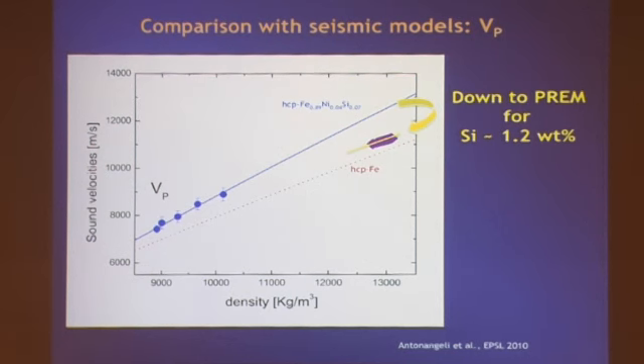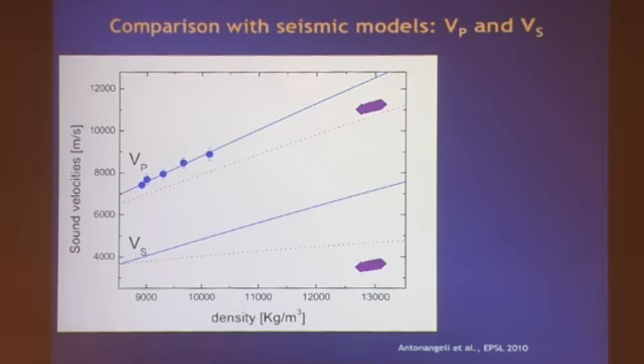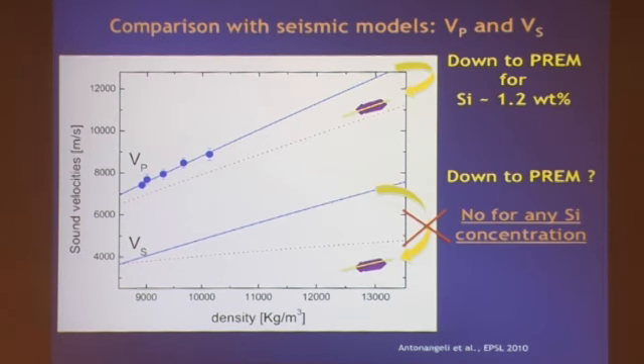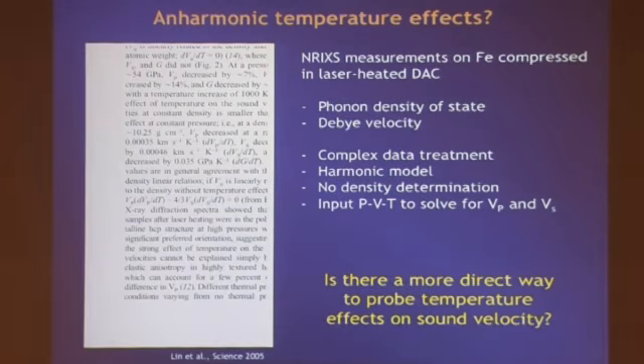So far so good. But what about VS? And here is where the problem comes. As you can see, both pure iron and iron-nickel-silicon alloy have sound velocity significantly faster than PREM. And at this point, it's clear that we cannot play with the silicon content to bring these things down. So we need to look for something else, and that is the effect of high temperature.